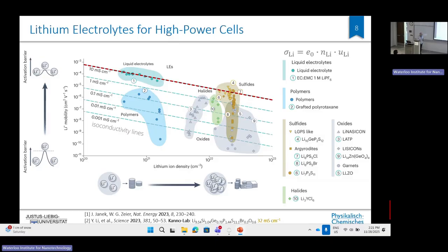So for the moment, let's have the ambition to meet and to beat liquid-based cells. Then we have to go here. And you see true polymer electrolytes so far don't meet this limit. They have a mobility issue. What is important is that the liquid electrolytes, which are also organic electrolytes, have one advantage. They have a rather low concentration of charge carriers. In order to achieve the high conductivity of the inorganic materials, you have to go to relatively high charge carrier densities. That's why we made this a cost axis in the case of lithium electrolytes. Well, if lithium cost doesn't matter, then it doesn't hurt. In the case of sodium, which I will not discuss today, this is not a cost axis, because sodium ions are cheap. So I think the picture is not so different for sodium electrochemistry, but for lithium, it's the way.